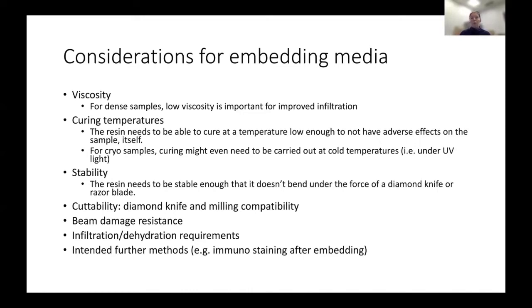Curing temperatures. So you want to make sure that the resin you're working with cures at a temperature that does not exceed causing damage to your sample. Many resins cure around 60 degrees Celsius, which for a living biological sample would be uncomfortably hot. But once it's chemically fixed and heavy metal stained, 60 degrees does not seem to cause damage to electron microscopy samples, biological samples.